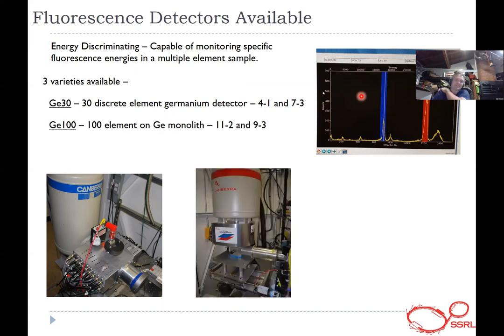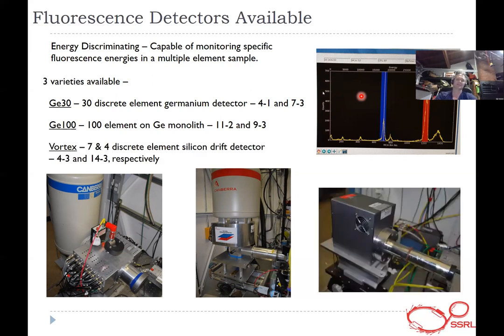We have a 100 element detector, and this is a germanium monolith. So it means it's a single chunk of germanium that's not segmented, but it has 100 unique electronic contacts in the back, creating like a pixelated detector. And so you can count a lot more photons, and this excels in the really dilute regime. So low PPM, or hundreds of PPM sample concentration, and they're available at 11.2 and 9.3.